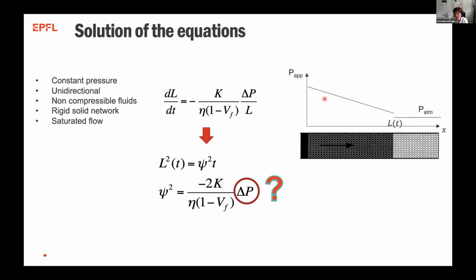And so we can write it here. We can solve the equations. We can replace this dP over dx by delta P over L, and then we just need to solve this very simple equation. We find that L, the flow front position, moves with the square root of time, or L squared moves with time. And this coefficient is proportional to permeability and delta P, and inversely proportional to viscosity and 1 minus VF. Now, what is this delta P?